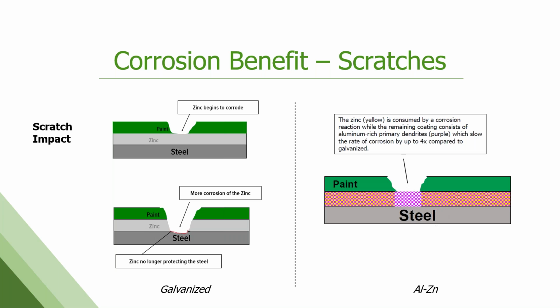So I've tried to put some little graphics here to explain the difference between a galvanized product and this aluminum zinc product, and why the one is better than the other. So forgive my attempts here at artistic ability. On the left is we're trying to demonstrate what happens if you have a painted coated steel product and you get a scratch in the painted surface, right, down to that metallic coating. So now you have exposed zinc.